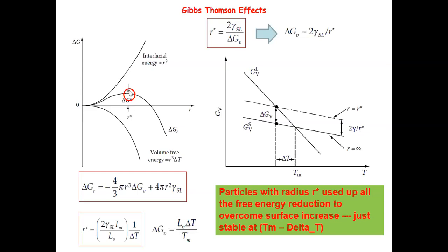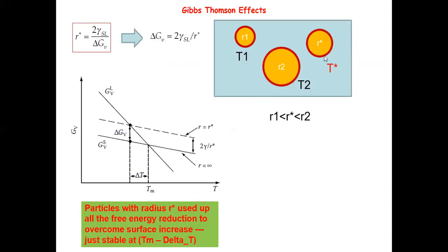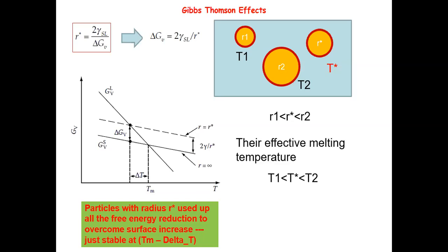So you would need some fluctuations that are at least as large as this delta G star to give you a nucleus at least as large as this guy, right? And then you can further grow. So this means that my delta G star is a very key energy consideration, an energy barrier, that contributes to the nucleation, because any nucleus smaller than this wouldn't actually contribute to the phase transformation. Does this analysis make sense to everyone? Okay, so I have to assume that makes sense and move on.